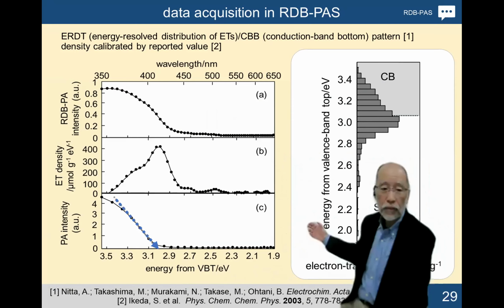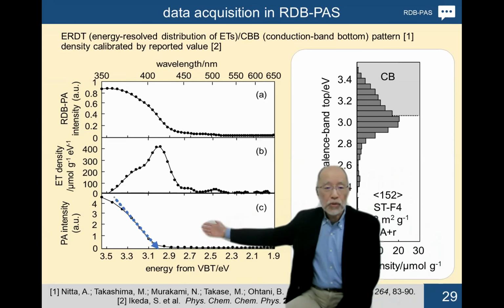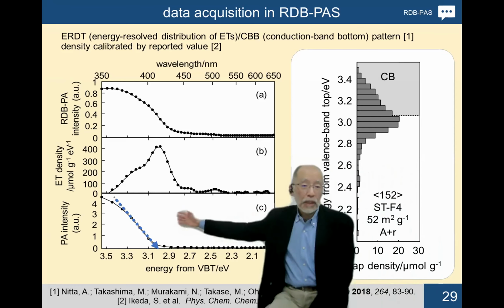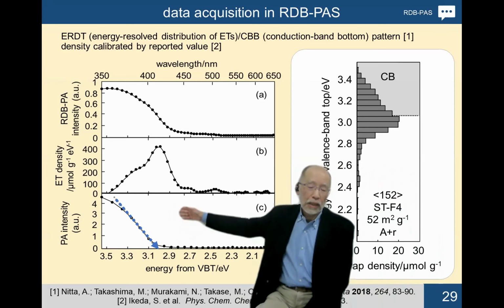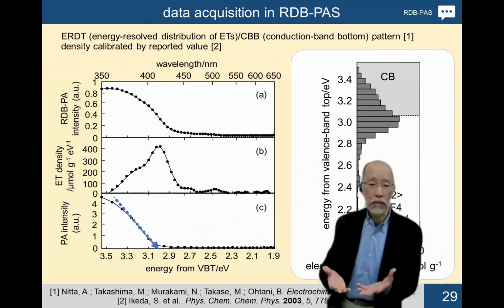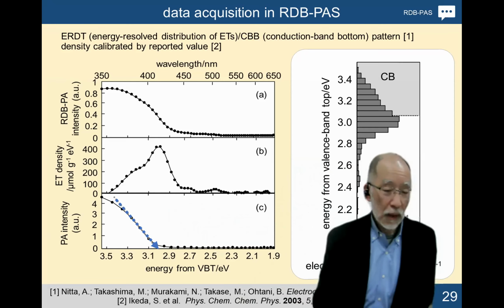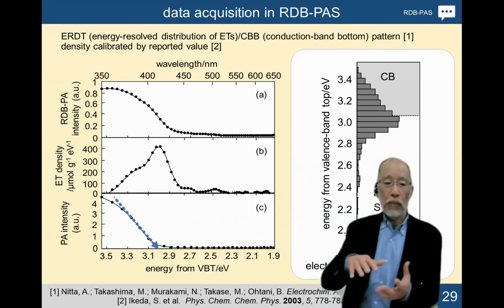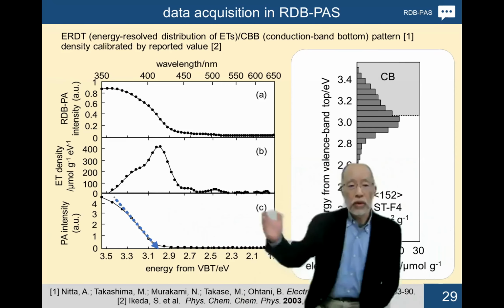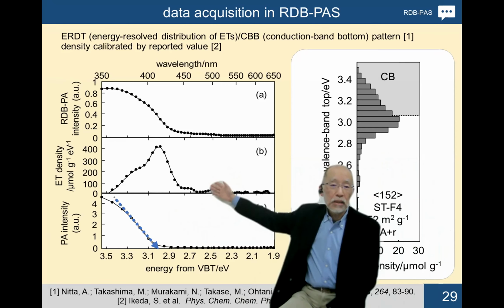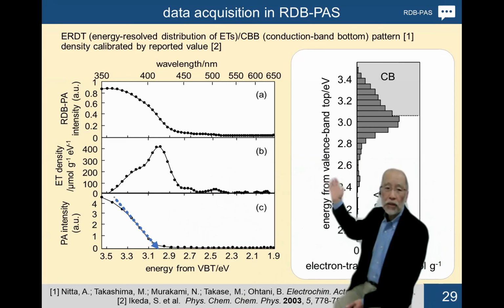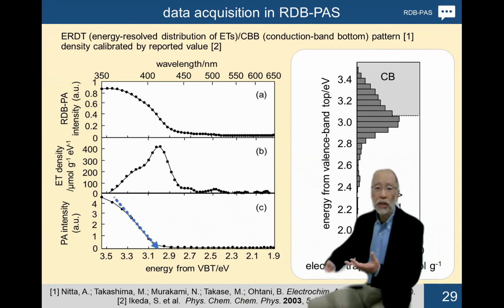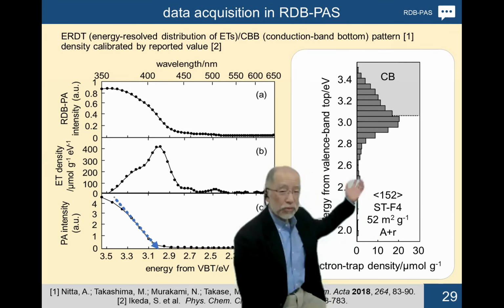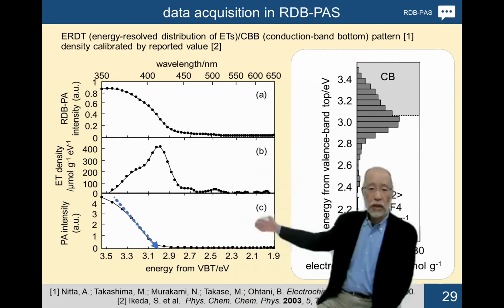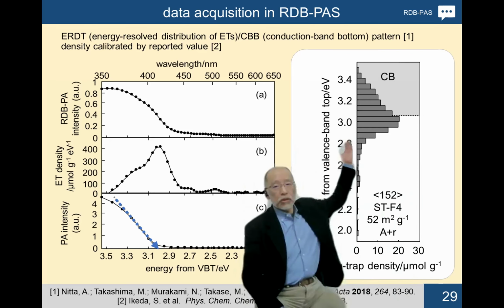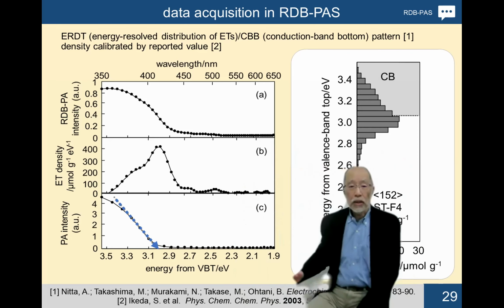Using the same setup, we can measure the photoabsorption like a PA spectrum. By interpolation of this linear line, we can determine the photoabsorption edge wavelength, and this can be used as band gap data. The electron trap distribution, ERDT, is plotted against the valence band top position because electrons in the valence band are excited to electron traps. So from the band gap energy data, it is possible to show the CBB position as a line on the same scale.